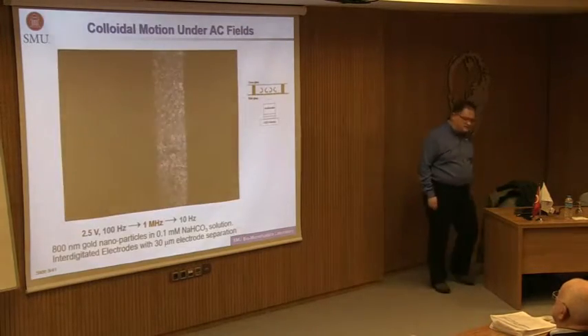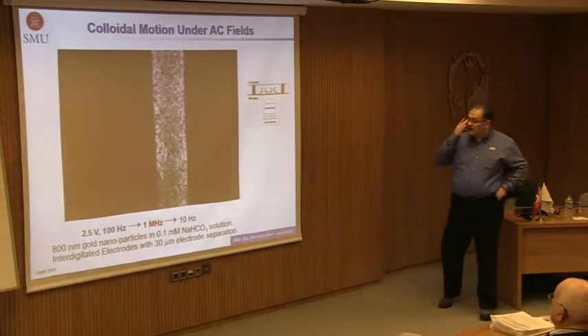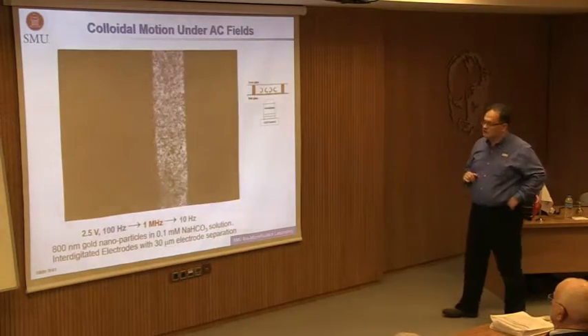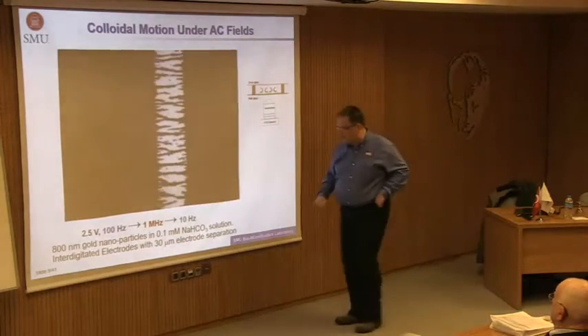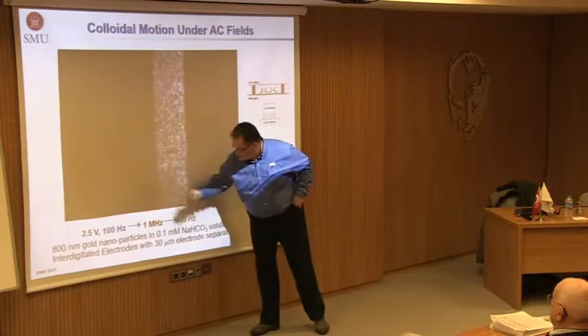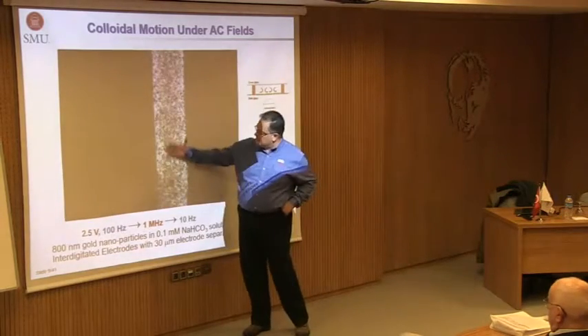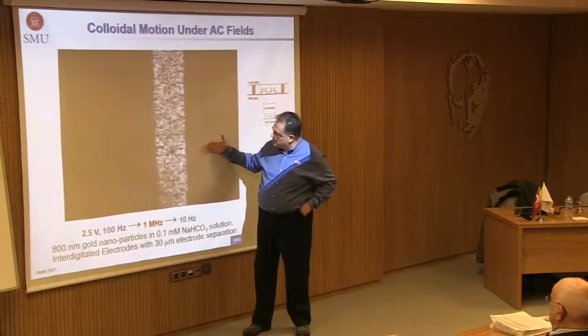So in order to show you what is possible, here's a movie, and we're using 800 nanometer gold nanoparticles in a given solution, and the gap between the electrodes is 30 microns. This is the glass part, this is the gold part.